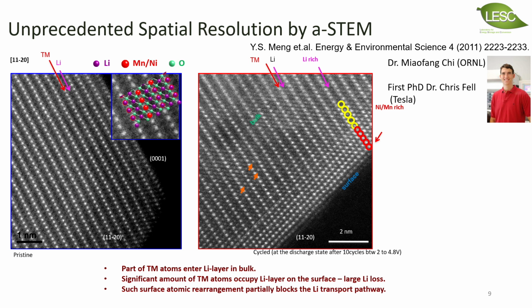And when we look at the materials under the microscope, these are not simulations. These are real microscopy images of the battery materials. In the zone axis, every bright spot you see is a column of transition metals that are arranged perfectly in the crystal. And lithium, because lithium has no electron density, appears very dark. And these are the superhighways for lithium transport.